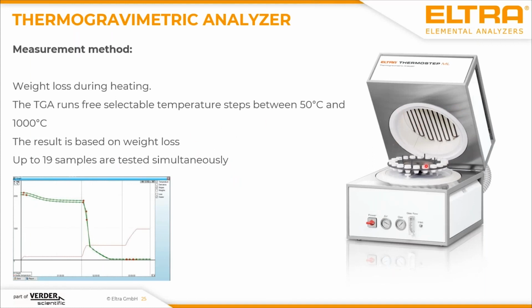So we have it here. This is the furnace part. So this here is the furnace. Here you see the heating elements. This furnace can heat up to 1000 degrees centigrade. And here we have our crucibles. And in this crucible, you put your sample. Here is the balance. This here is the pedestal of the balance. And then this table turns, and every time when a new crucible comes during the turning process, we look at the weight of the sample, the mass of the sample, and we do this in several steps.